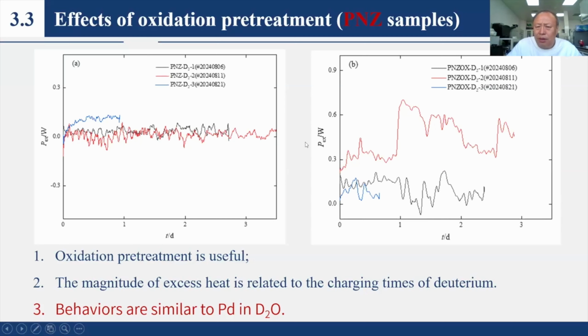This behavior is similar to our experience with palladium in heavy water. First, the pretreatment is important. Secondly, the activity of the sample is not constant. The first time might not work, but the second time gives the best result. Of course, sometimes it is the third time. But after repeated runs, the activation will disappear.